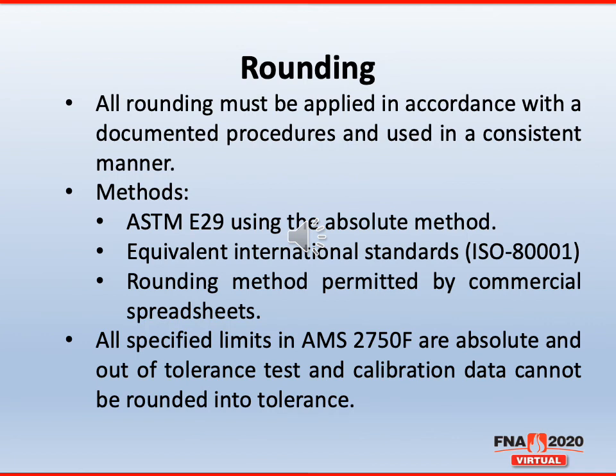So everyone's favorite topic in AMS 2750 when it came out in Rev E was rounding. And we finally addressed rounding in Rev F with a little more clarity and better understanding. First off, all rounding must be applied in accordance with a documented procedure and used in a consistent manner. So you are allowed 3 different methods of rounding: ASTM E29 using the absolute method, or an equivalent international standard such as ISO 80000-1 Rule B, or you're allowed to round per any commercial spreadsheet. So the way we learned in school, where 0.5 rounds up, as done by a commercial spreadsheet, we are allowing that as long as this is documented in a procedure and always used in that consistent manner.